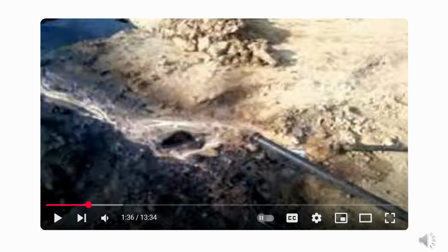However, given time, the black cloud would settle to the bottom of the drill pit, forming a black layer in the bottom of the drill pit. The black material at the bottom of the drill pit was magnetic and could be separated from the salt water using magnets. In this slide, I am using magnetic separation to recover the magnetic material.